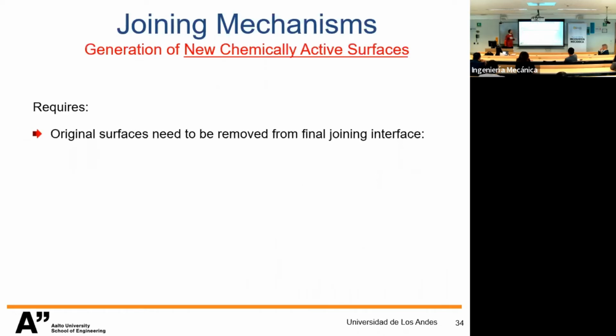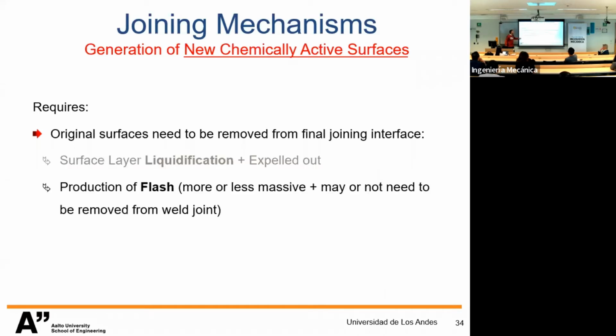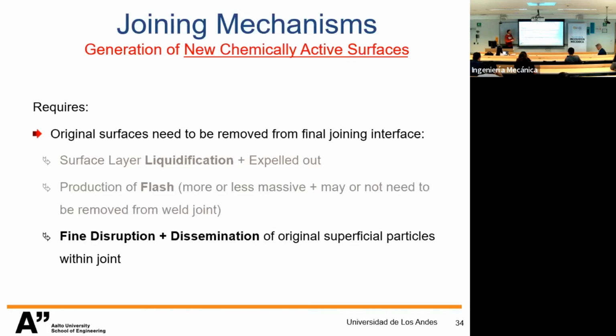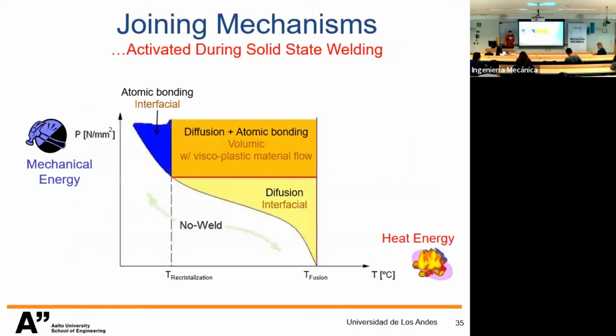So, a new chemically active surface requires that we get rid of the original surfaces. We do it by liquidification or expelling out, heating the interface and getting the new chemically active surface behind, or bringing the inside material to the outside by plastic deformation. Every time we have these locations at the surface, we expose new chemically active surface that is looking for a new balance. Or we can keep the original surface. We break the original surface into very small, fine amounts that we then disseminate inside of the processes, so that the togetherness doesn't play well.